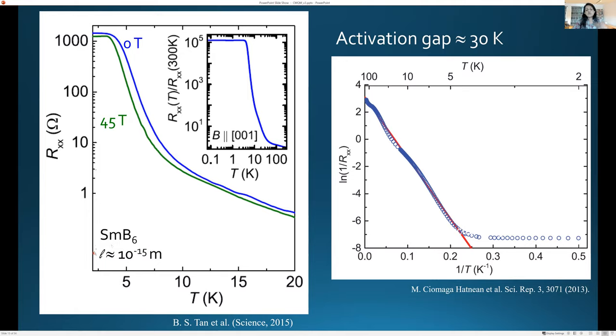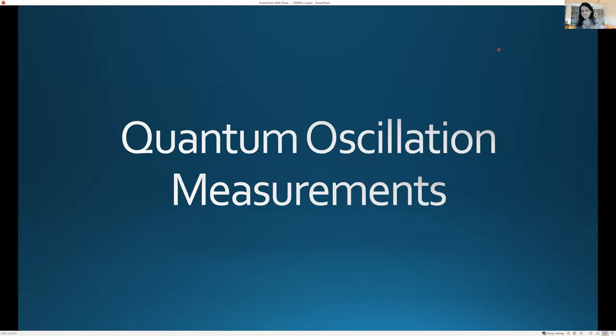And if we were to try and attribute mean free paths to it, the electrons are barely moving. So you would associate something like 10 to the minus 15 meters, which means that this is very far from a metal. The electrons are largely in place except for very small movements. And this is just a fit to the activation gap, which is about 30 Kelvin. Okay, so given all that to, you know, make you confident, this shows properties of an electrical insulator.